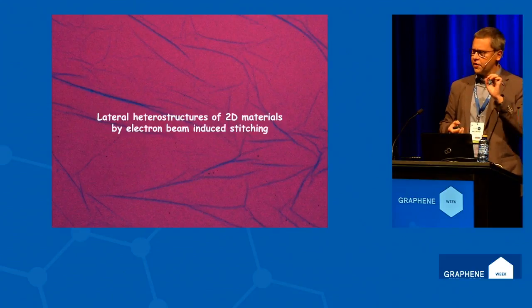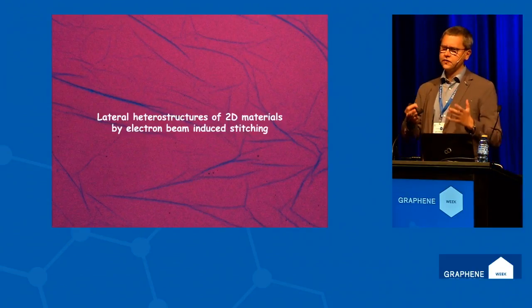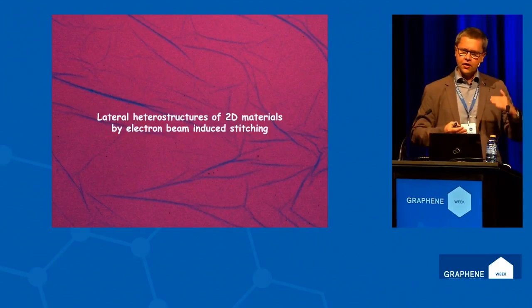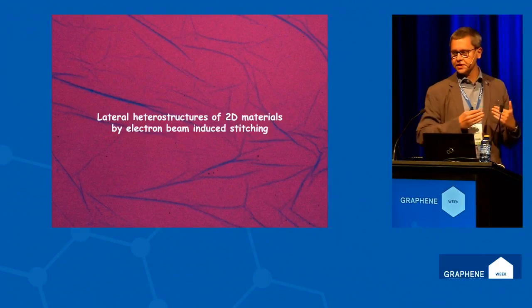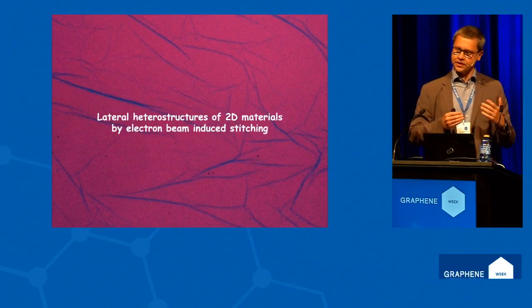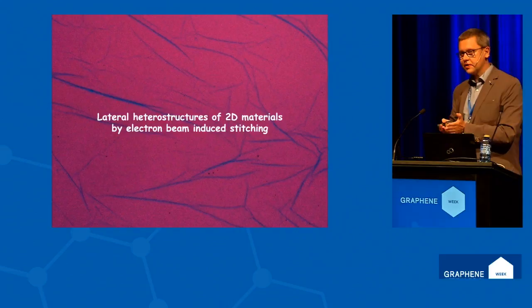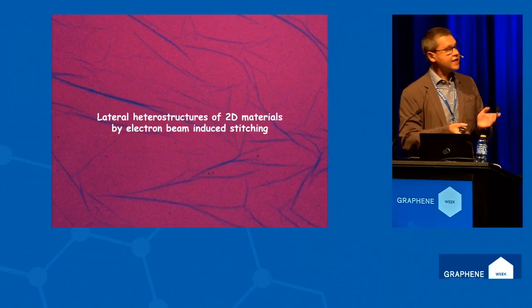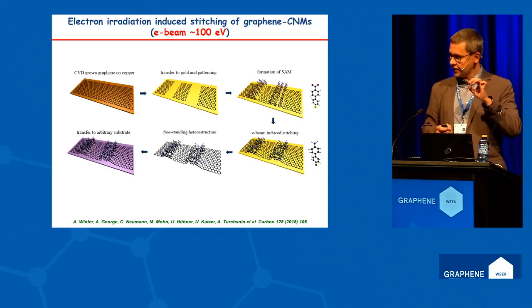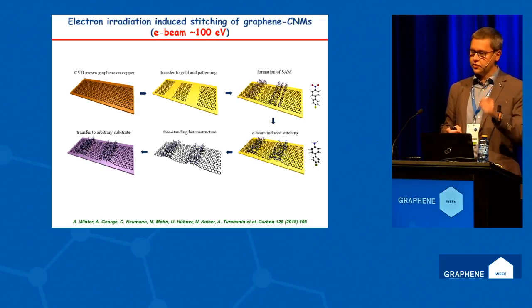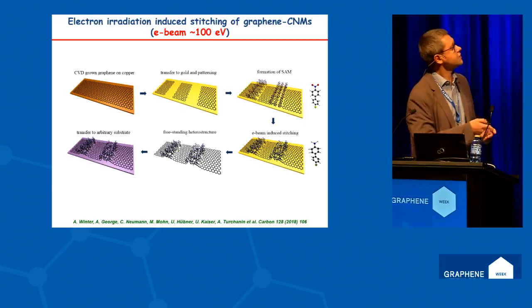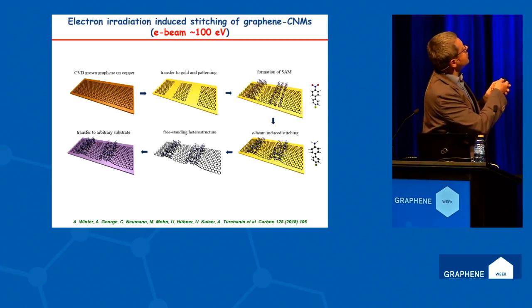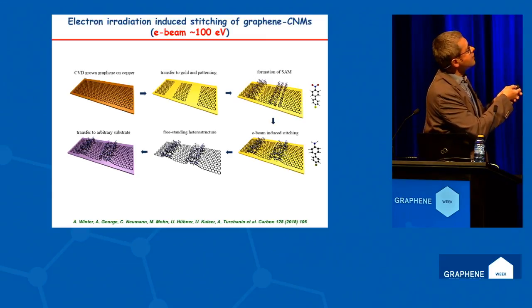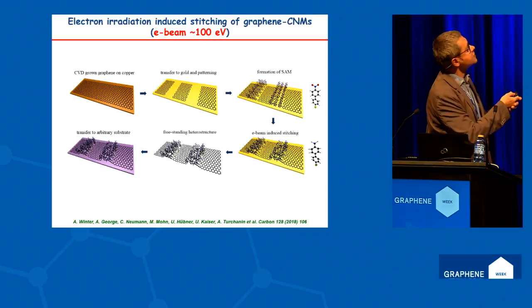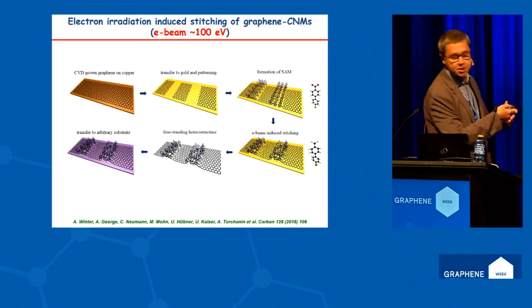How far can you go with this electron beam induced synthesis? There are a lot of talks and a lot of work at present on synthesis or assembly of vertical heterostructures, but there are not so many talks on the synthesis of lateral heterostructures because of some fundamental problems. You can overcome, at least in some cases, this problem by again inducing an electron beam induced chemical reaction. As shown schematically here, you start with a graphene sheet. This graphene sheet can be patterned by lithography. Then the free areas of graphene can be filled with molecules by irradiation with low-energy electrons.